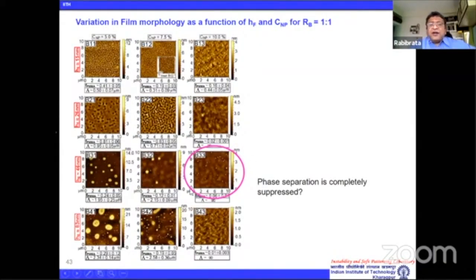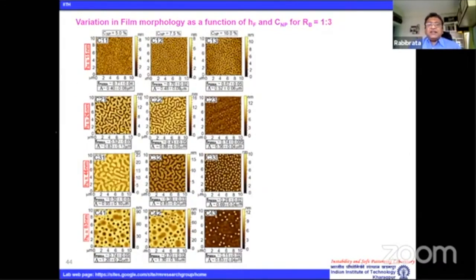You add some nanoparticles and you see the phase separation is almost suppressed. So if the phase separation is suppressed and you have two phases, what exactly is happening? Either you are creating a bilayer, an in situ bilayer, or you are somehow arresting the spreading, so a 50% phase occupies 50% only. I'll skip all the detail. So we looked in detail into this particular sample.